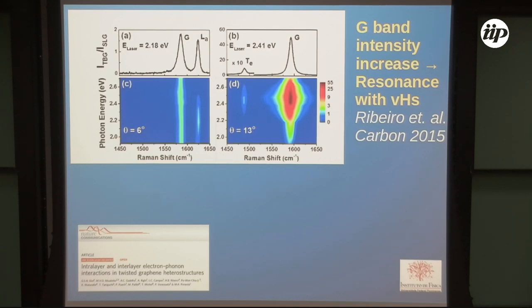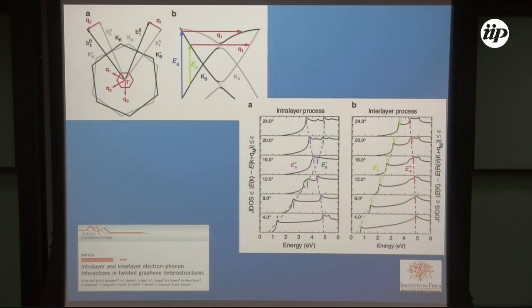So from the electronic point of view, they clearly have different origins, okay? I don't have much time now, but what we did was calculate a kind of joint density of states. Basically, we calculate the density of states of this point multiplied by this point, okay? In two kinds of processes. So here, in black, we have the electronic dispersion of one of the layers, and in gray, the electronic dispersion of the other layer. So I can, in principle, have in twisted bilayer graphene electron-phonon coupling processes from black to black, meaning the same cone, or from black to gray, meaning from one cone to the other cone.